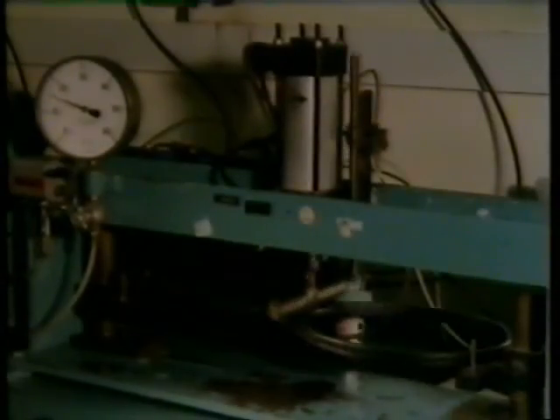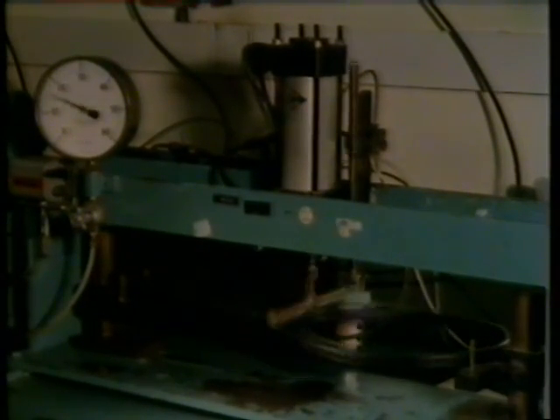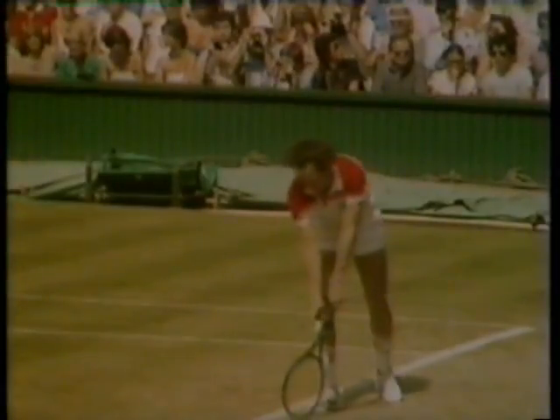The problem is how to get the metal out. Well, this is a very special metal which melts at 150 degrees centigrade, lower than the melting point of the carbon fibre and nylon. So by heating up the moulding, the metal melts and simply runs out at the end of the racket. If we cut open a frame from which the metal has been melted out, we can see that at each string hole there is a pillar running from the inner wall to the outer wall, and this gives the racket extra strength. The injection-molded carbon fibre racket is more than strong enough for all the tests designed for the wooden racket, and it also survives the most important test of all.